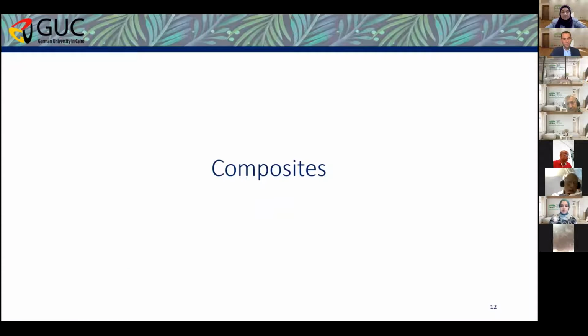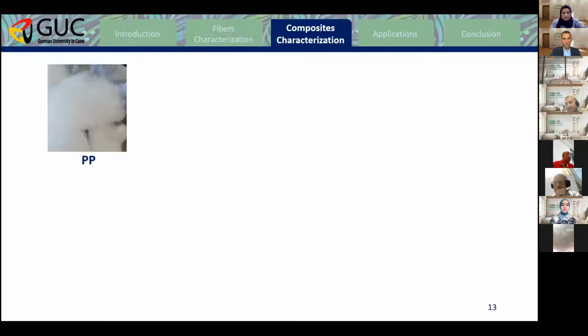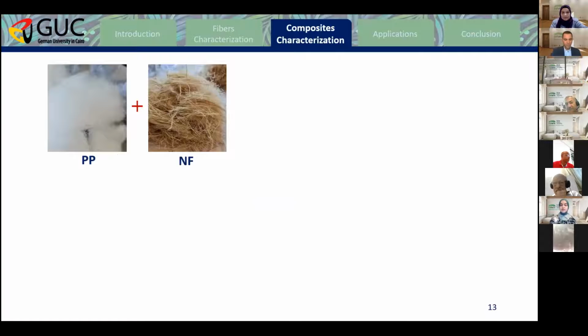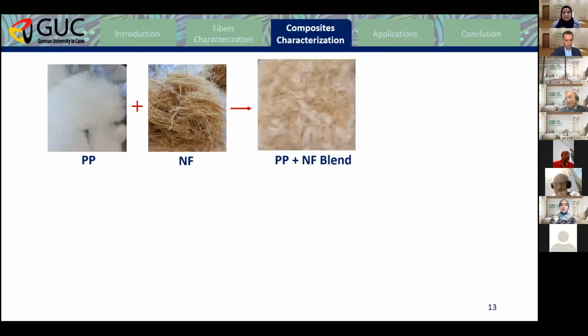Moving on to the composite manufacturing and characterization, 50% polypropylene in fiber form was blended with 50% natural fiber, and specifically this weight percentage was chosen since this is the most commonly used weight percentage in the automotive industry that renders high mechanical properties, lightweight, and good acoustic properties. These fibers were blended together to give this polypropylene natural fiber blend.